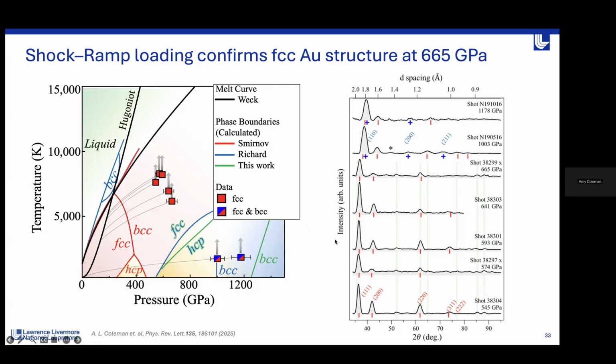We went to quite some pains to look at this. There were a few iterations of target designs. One of the considerations in these types of experiments is obviously, if you have a multi-layered target, you need to be careful of overlapping diffraction peaks. We have some peaks in our profiles here that are from our platinum calibrant, which is uncompressed.